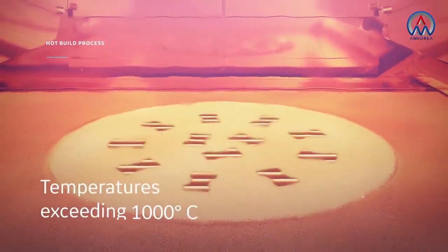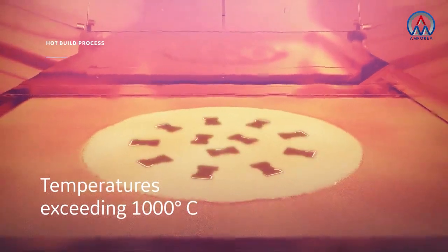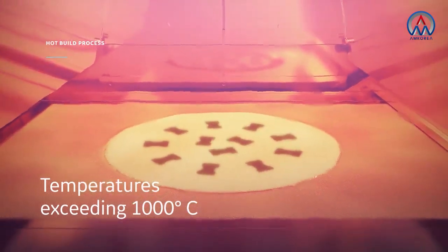The build environment is kept hot, reaching temperatures exceeding 1000 degrees Celsius, resulting in no residual stresses and allowing for the processing of crack-prone materials.